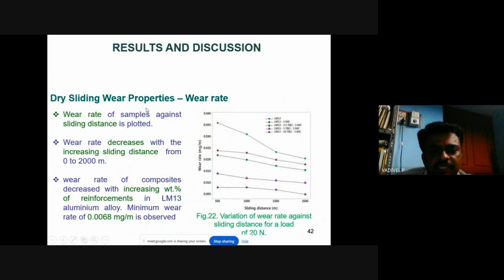In the dry sliding wear properties, the graph is plotted between the wear rate and the sliding distance. The wear rate of samples decreases with the increase in sliding distance from 0 to 2000 meter. The wear rate of the composites decreases with increasing weight percentage of reinforcement in LM13 aluminum alloy, and the minimum wear rate of 0.0068 milligram per meter is observed in the study.